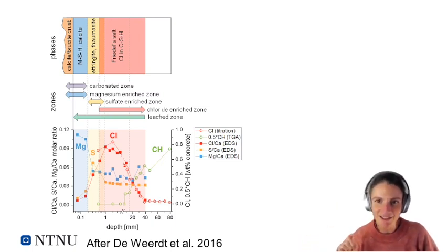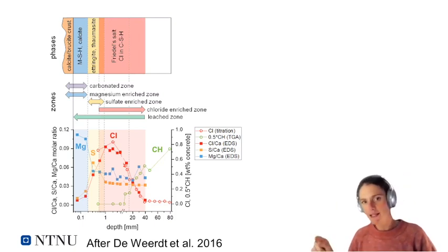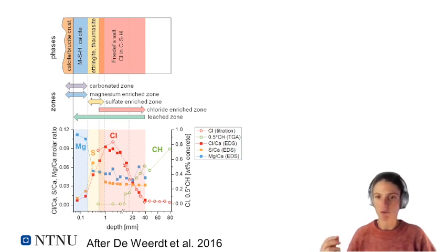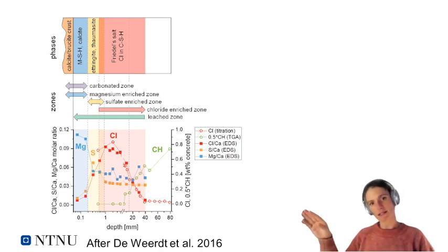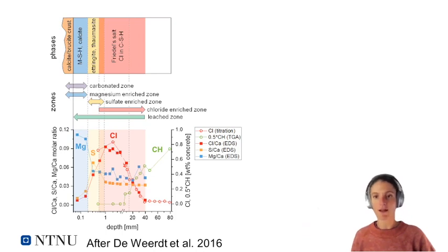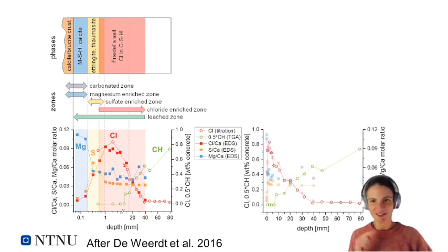Again, the beginning of the horizontal axis is in a logarithmic scale, so we're really zooming into what happens on the surface, whereas the second part is a linear scale. And there I'm matching the EDS profiles with profiles I have from titration. The traditional way of looking at chloride profiles is by chloride titration. And you can also see there a decrease in the Portlandite profile, the green profile, showing that there's leaching in these samples. So we're losing Portlandite towards the surface. Just for clarity, I once more add the same graph where the axis is totally linear, and then you see that the sulfur and magnesium changes are very, very close to the surface.